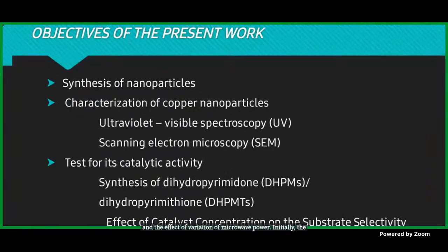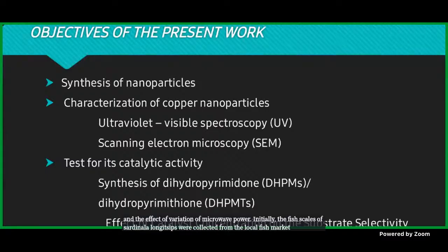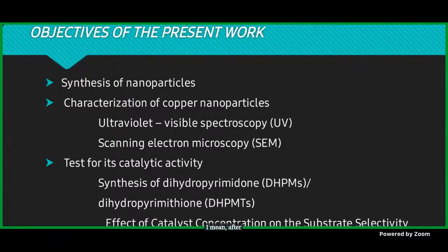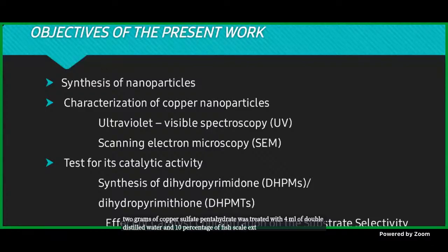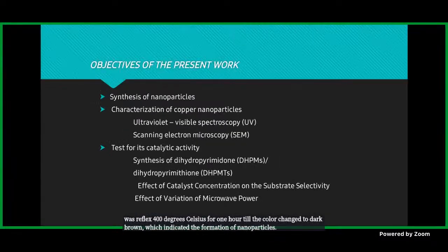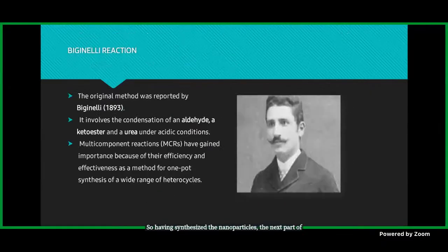Initially, the fish scales of Sardinella longiceps were collected from the local fish market and washed with distilled water. After drying, they were finely powdered and boiled in 450 ml of distilled water, heated at 80 degrees centigrade for 30 minutes, after which it was centrifuged. The copper nanoparticles were prepared using copper sulfate pentahydrate, wherein 2 grams of copper sulfate pentahydrate was treated with 4 ml of double distilled water and 10 percent fish scale extract was added to it. It was refluxed at 100 degrees Celsius for 1 hour till the color changed to dark brown, which indicated the formation of nanoparticles.